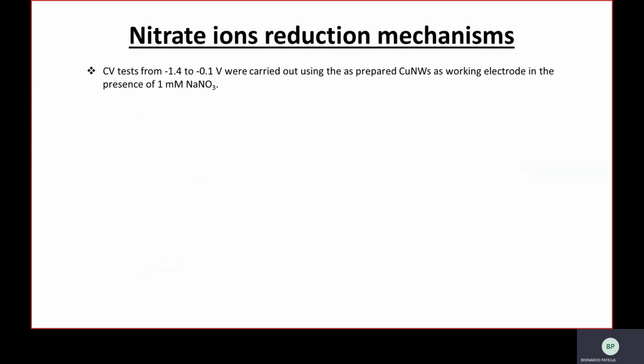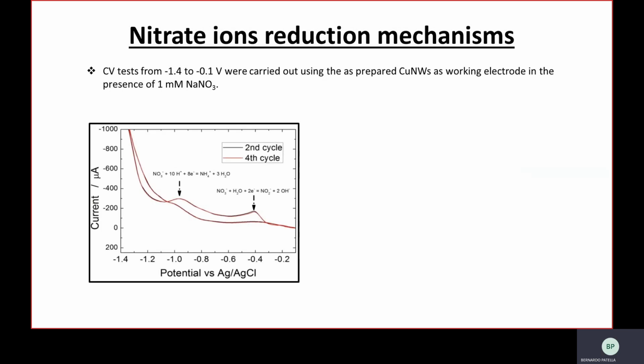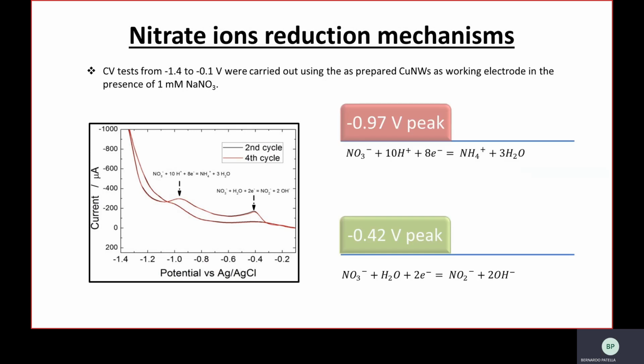To better understand the detection mechanism, a cyclic voltammetry was carried out in the potential range from minus 1.4 volt to minus 0.1 volt in a solution made of 1 millimolar sodium nitrate. Two distinct peaks were found at potentials of about minus 1 volt and minus 0.4 volt. These two peaks correspond to the reduction of nitrate to ammonia and nitrite, respectively.